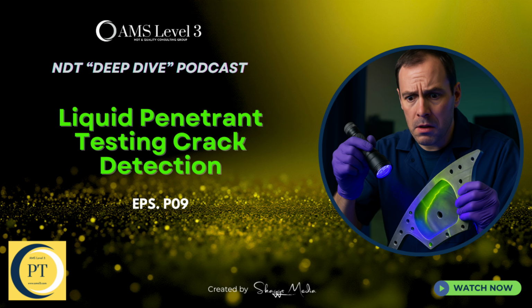What if you're out in the field, maybe doing a portable inspection? Then you'd likely use solvent removable, which is method C. And the absolute rule here is you apply the solvent only by wiping with a clean, lint-free cloth that's dampened with the solvent. Dampened, not soaked. Right. You never flush the surface with liquid solvent. That would just dissolve and wash away everything, including the penetrant and the flaw. Strictly prohibited. Gotcha. Wiping only.